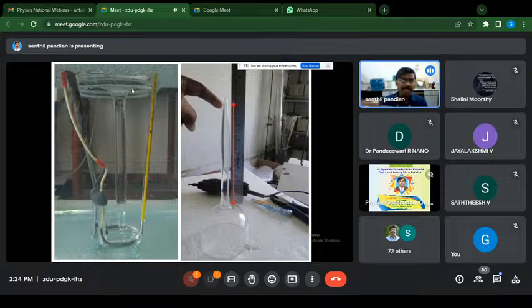We cannot stop immediately, otherwise multinucleation and microcracks will form in the grown crystal. We have to reduce the temperature by about 0.1 degrees Celsius per hour or 0.5 degrees Celsius per day, depending upon the solubility of the material. You have to select the cooling rate of this growth run. So we have to wait until it reaches room temperature.